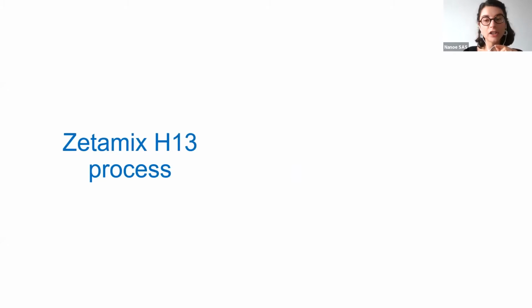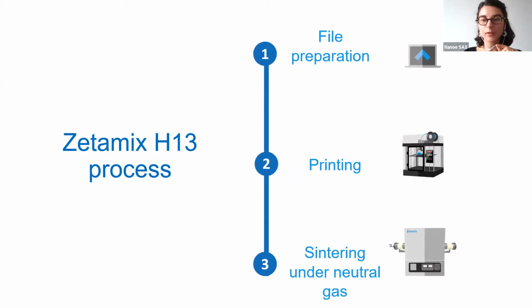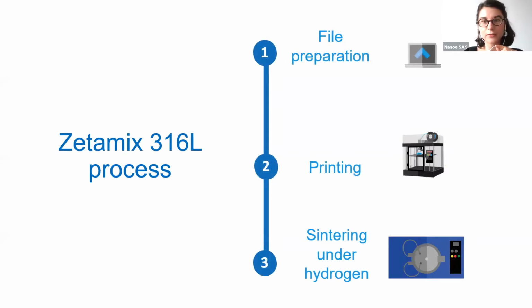I'm going to focus now on each process for metal. First, the H13 process. It's an easy process with 3 steps. First, the file preparation and the printing, the same as with polymers, PLA or ABS. And the last step is the sintering under neutral gas. It's very important to make sure that your part has its final properties and its final density of 95%. For the stainless steel, it's slightly different. The first 2 steps remain the same, with the file preparation and the printing, but the sintering is under hydrogen, so you need a special furnace, whereas with H13, the Zetamix furnace is a good furnace to sinter the parts.